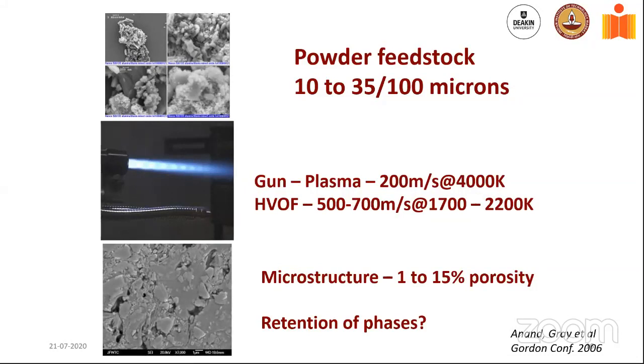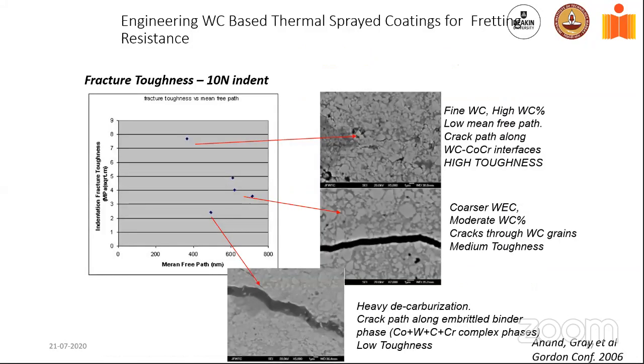And depending on the temperature that the parts saw, you can either have parts with all the carbides retained, or you can have coatings with quite a bit of the carbides dissolved into the binder. And that essentially gives you coatings with different properties. So that's what you're going to see in the next slide, which is engineering tungsten carbide-based thermal spray coatings for fretting resistance.